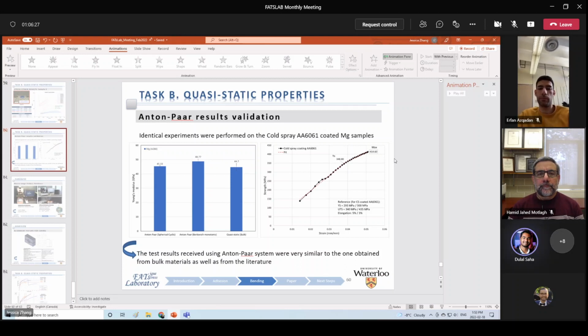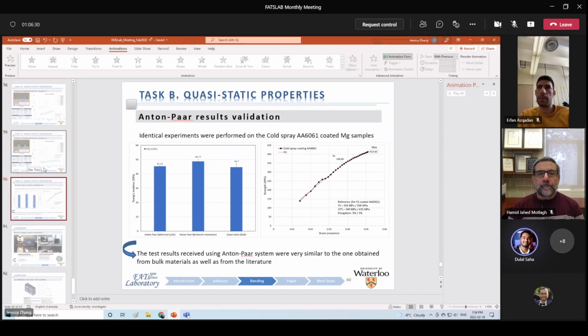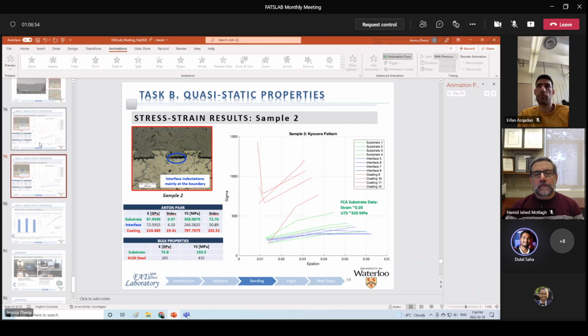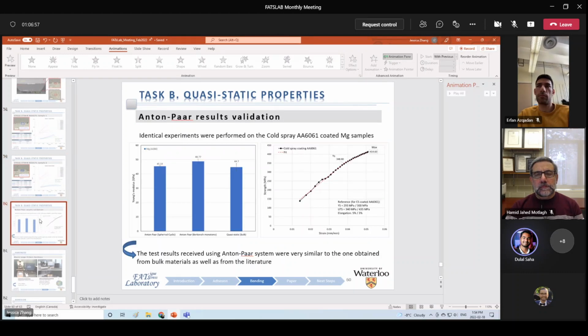So this curve here is the representative of the stress strain curve. You cannot compare it with the bulk sample stress strain curve, but it will give you some representation. I cannot tell how different the representative stress strain curve is from the real tensile test, but you cannot compare the values you get after plastic deformation. Within this elastic region, however, you can have a better estimate of the property.